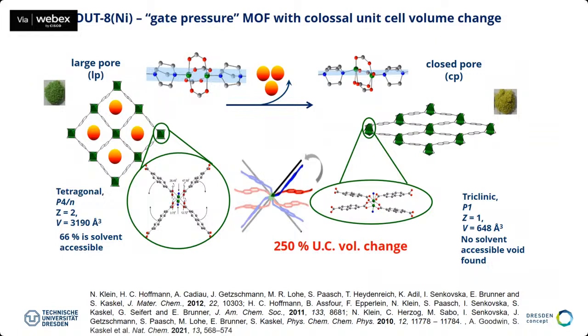But in this contracted structure, the paddle wheel is quite distorted. And you see this here also, that the axis between the nickel atoms is a bit off. And this also induces this color change. You have different colors for the closed pore and for the open pore form. And this material shows the huge volume change. The unit cell volume changes by more than 200%. This is a record in the field of flexible metal organic frameworks, and this is a typical characteristic.